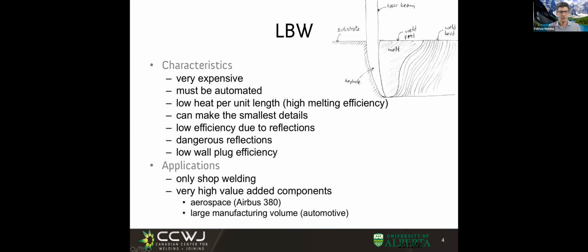Something interesting about lasers is, although we say it's a high energy density process, and it can even be a high power process, 9 kilowatts is high power. Welding with an arc at 9 kilowatts is a very big arc. However, because it moves so fast, the amount of heat per unit length, the heat input, which we discussed in terminology, tends to be low. What a paradox. You have a powerful process, but it gives you low heat input. And low heat input means low distortions. It also means very fast cooling, which can be a problem in some cases.